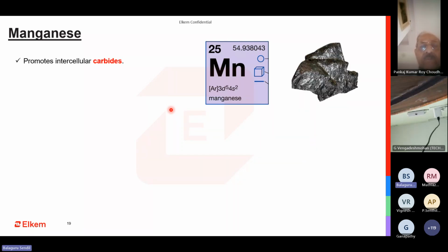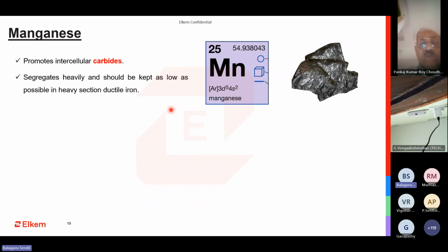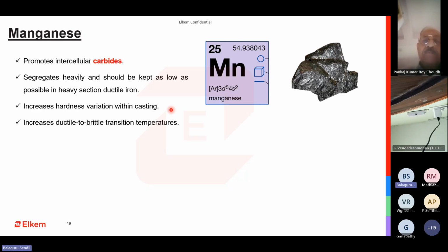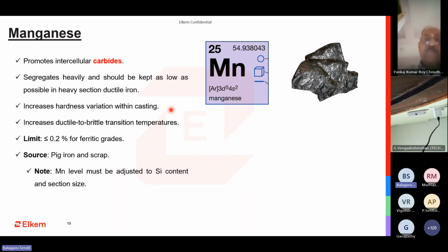The last one is manganese. Manganese, I would not call a trace element at this point. It is actually a part of the ductile iron system, but I have mentioned it here because we are seeing a lot of steel scrap with manganese, which is the primary element. Only then do they try to add titanium and boron. So manganese is the first thing that they add. It promotes intercellular carbides in thick sections and segregates to the grain boundaries, especially in ductile iron, leading to a lot of porosities and inclusions, which will affect your mechanical properties, especially the elongation. It increases the hardness variation within a casting, and for ferritic grades it is very advisable to keep it as low as possible.